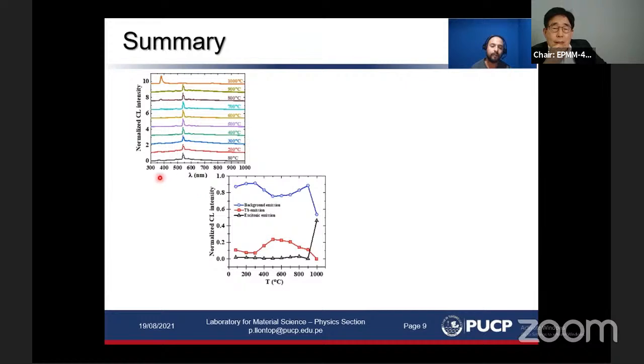Okay, to summarize this talk, we have seen that we obtained the terbium-related emission, the characteristic terbium-related emission, and for a temperature at around 300 degrees Celsius in thermal treatment, there starts an increase of the terbium-related emission. So we believe that there is an optical activation of these ions, so their intensity is increasing.